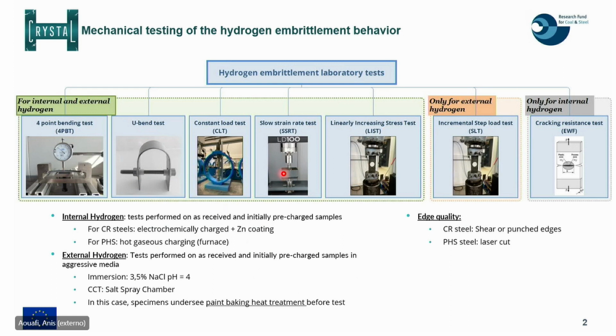The two other tests are the slow strain rate test, or the linearly increased stress test, and this uses a tensile machine in order to apply a constant increase of loading at various strain rates. The other test that has been used is the incremental step load test, and for this one we also use the tensile machine in order to apply an incremental step loading during the test. The last test that has been used, well introduced this morning in the toughness project, is the crack resistance test, the essential work of fracture, and we will show you some results using this test in the hydrogen embrittlement field.